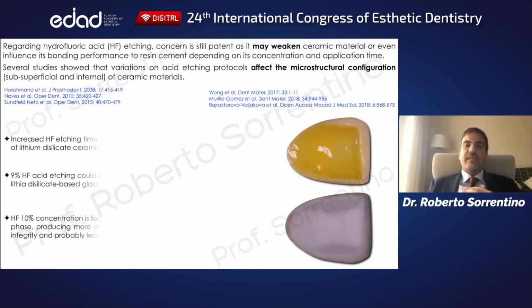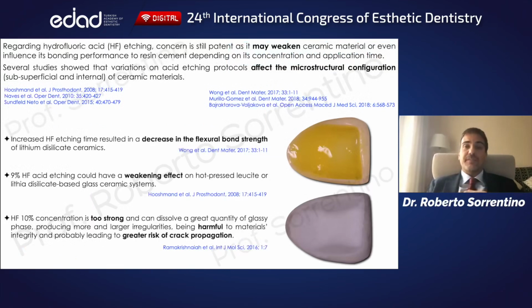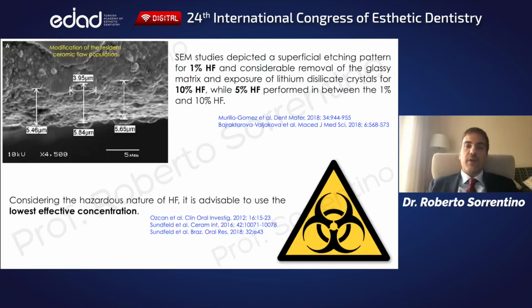Several studies prove that concentrations ranging between 9 to 10% are too strong. They may decrease the bond strength and weaken particularly lithium disilicate, increasing the risk of onset and propagation of microcracks within the material. Hydrofluoric acid is available in different concentrations, and laboratory studies showed clearly that 5% is enough to partially remove the ceramic glassy matrix with no weakening and creating an effective superficial etching pattern. Consequently, the lowest effective concentration should always be used.